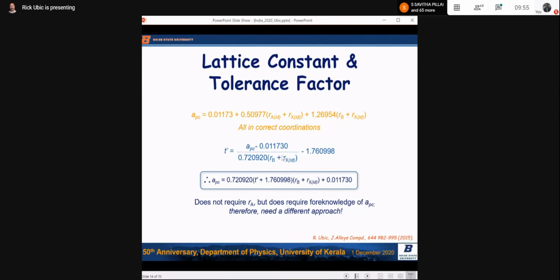So you can use this equation to calculate the lattice constant in terms of T prime. So we're just rearranging this equation, and PC is pseudocubic. So the pseudocubic lattice constant is this now. It's a function of T prime and the B-X bond length. So we require R_B, which we can get from the Shannon tables, easy. The ideal R_X, which is the Shannon anion size, we can get that easily. And of course, we need T prime.